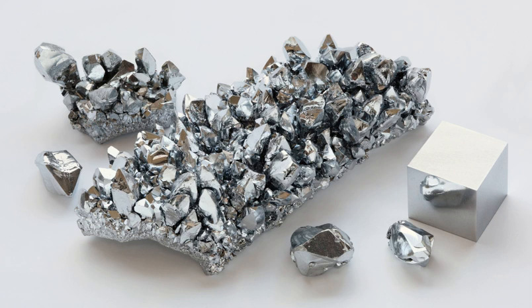Thin deposition involves a layer of chromium below 1 micrometer thickness deposited by chrome plating, and is used for decorative surfaces. Thicker chromium layers are deposited if wear-resistant surfaces are needed. Both methods use acidic chromate or dichromate solutions. To prevent the energy-consuming change in oxidation state, the use of chromium(III) sulfate is under development. For most applications of chromium, the previously established process is used.